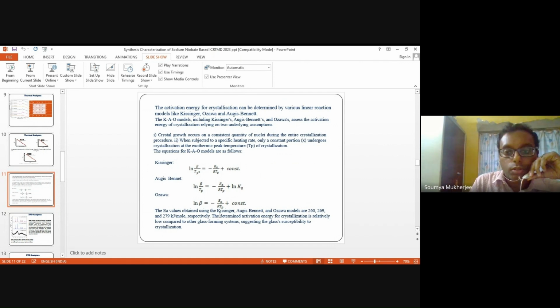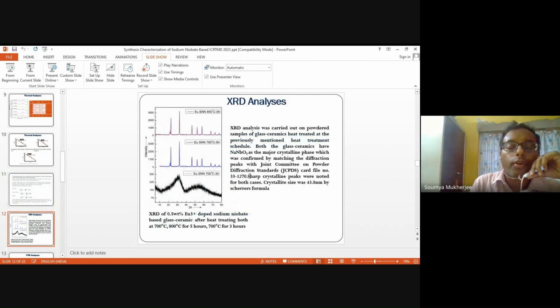Now, moving to the phase development. Following this, we have undergone heat treatment to get the glass ceramization. It is very interesting to note that at 700°C, though there are some small peaks, it is not that crystalline in nature. It is still showing a good hump, that is, amorphous.